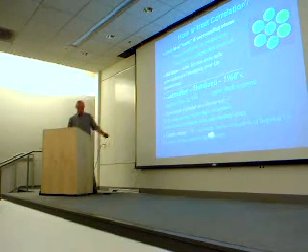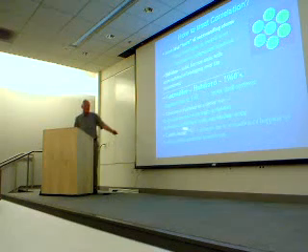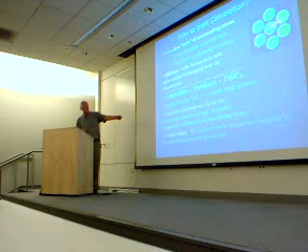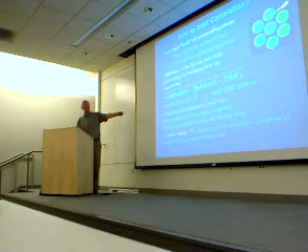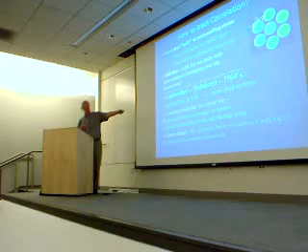But the key thing that would happen is that the kinetic energy, the bandwidth, would get decreased, because an electron on this site has its possibilities for hopping to neighboring sites reduced by the fact that there may be a strong Coulomb repulsion for an electron on the neighboring site, depending on whether another electron is there or not.